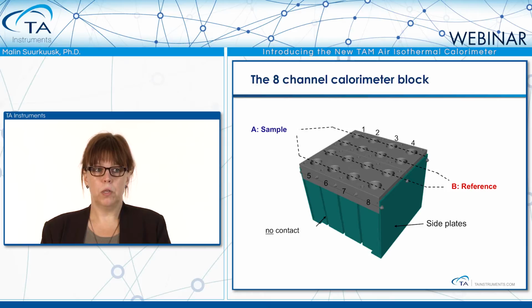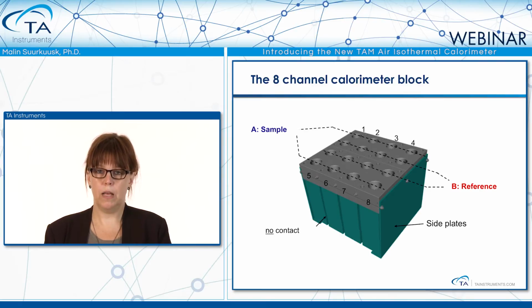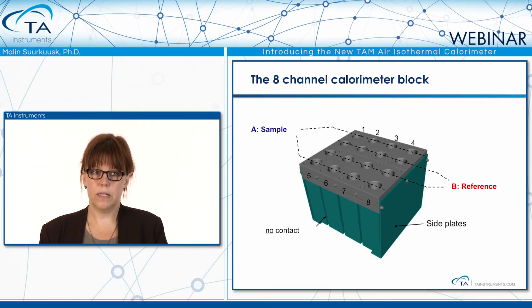And you see in the bottom, that says no contact. That's where the primary heat sink is, and the sample is actually standing onto that. There is no contact between the calorimeters in the bottom part, so we will minimize the crosstalk between the channels. In the top, all the secondary heat sinks are connected together to transfer away any disturbances from the surrounding. Also, to minimize heat flow, all the samples which are in the A sides are positioned on the outside, and we have the inert references pointing towards the middle.